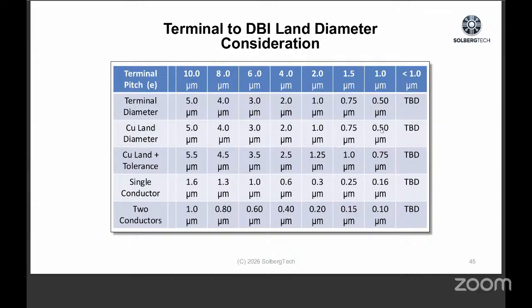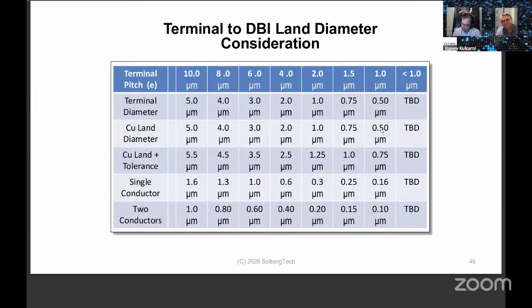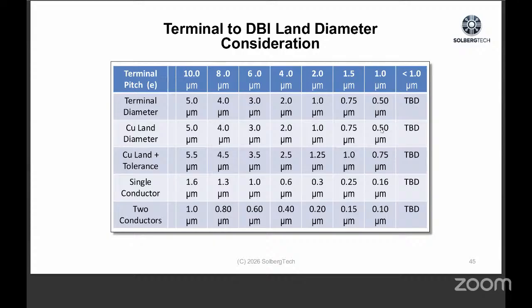But if you add tolerance for the machine and placement, we add a little more to that, and so I got 5.5 microns for the land. And then a single conductor could be 1.6 microns. If you have two conductors, they have to drop down to 1 micron each, which seems to be within the capability of the technology today. The copper conductors are formed with the semi-additive process. So they start with a seed layer of copper, and they actually plate the trace up on the copper and do a secondary etching to remove the seed layer. Next slide, please.